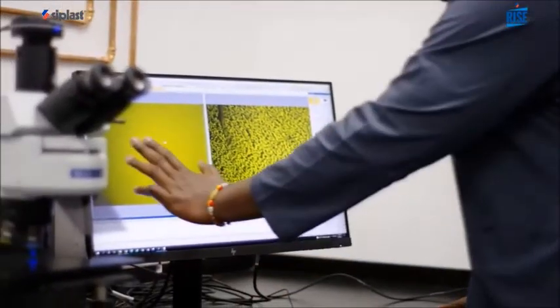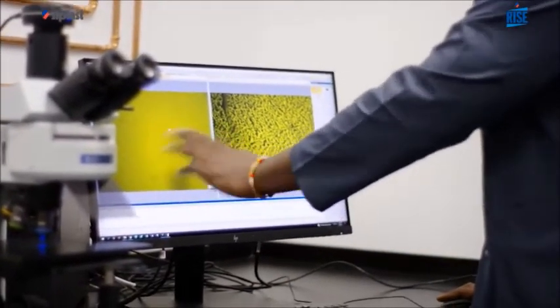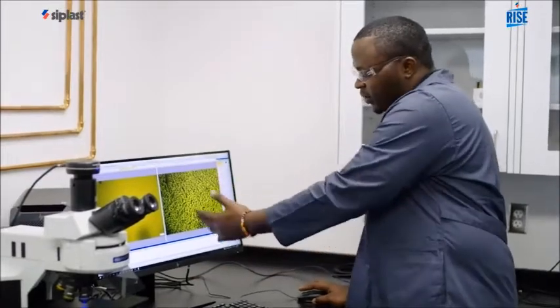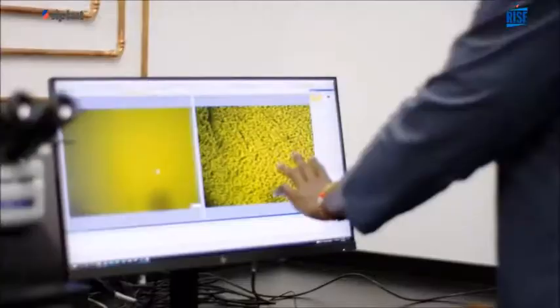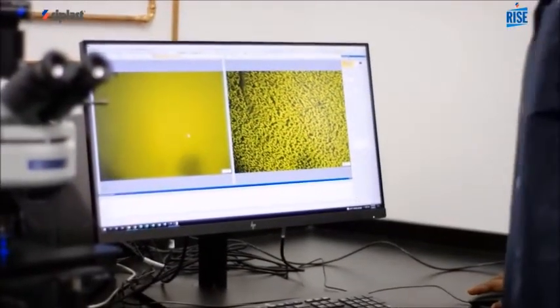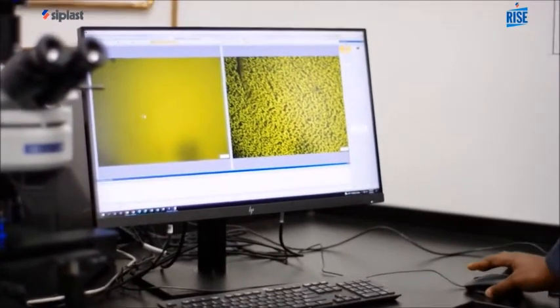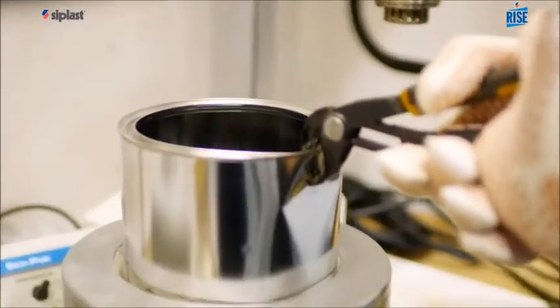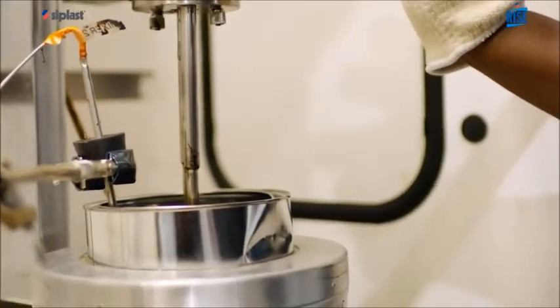Over here, we have two blends. One here shows a more smoother distribution. This one here is well distributed, but as you can see, it's a little bit not as smooth compared to the SA blend on the left. Some factors may include the mixing time, the mixing temperature, all those different things. So that's why, based on how we see the blend, we can then try to see if we can adjust, increase the temperature or mix the blend more to make it more uniform.